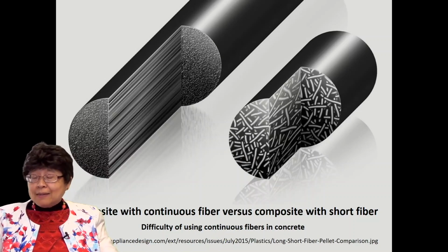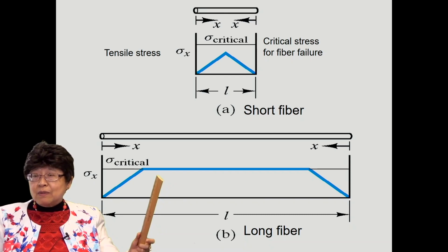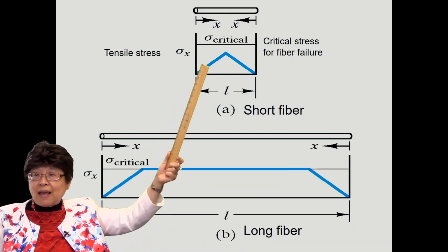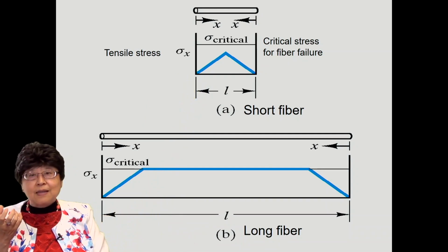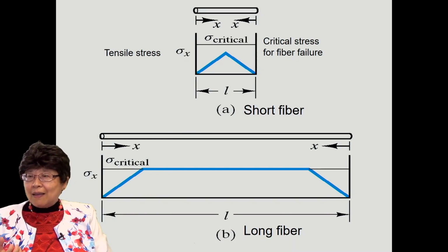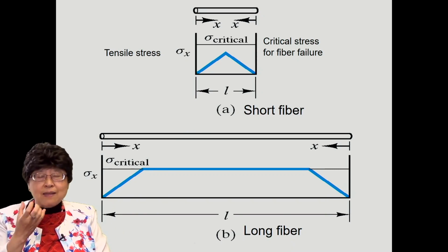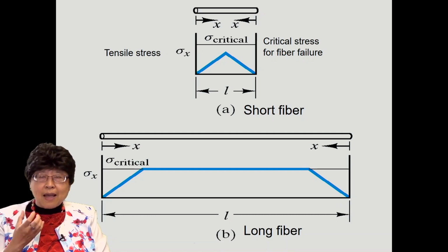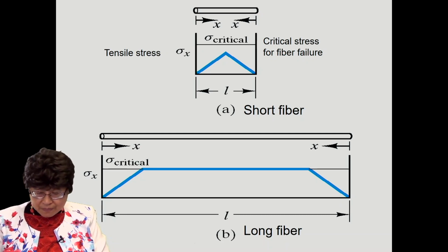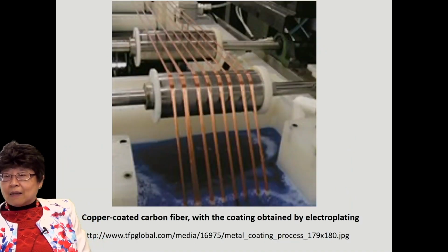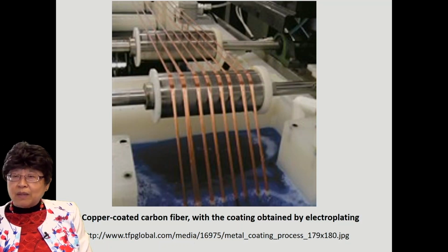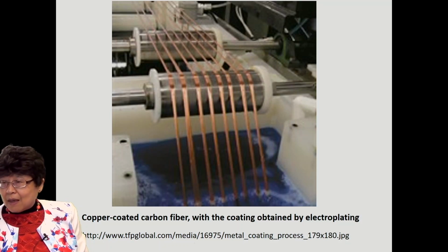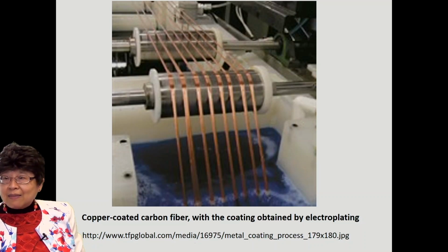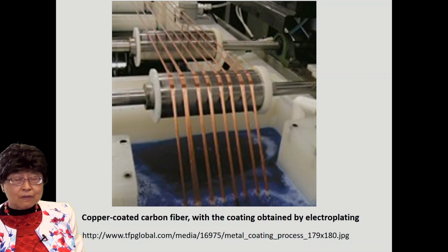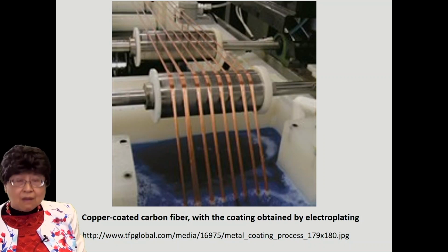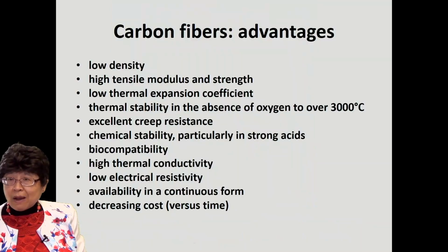On the other hand, in general, continuous fibers are more effective for reinforcing than the short ones because of the fact that the interface is not perfect. That is, the bonding at the interface is not perfect. Because of that, the long ones are actually more effective than the short ones. One can also coat the fibers with a metal such as copper or nickel, by a process such as electroplating, and that would greatly enhance the conductivity of the fiber. The metals are a few orders of magnitude more conductive than the carbon or graphite.